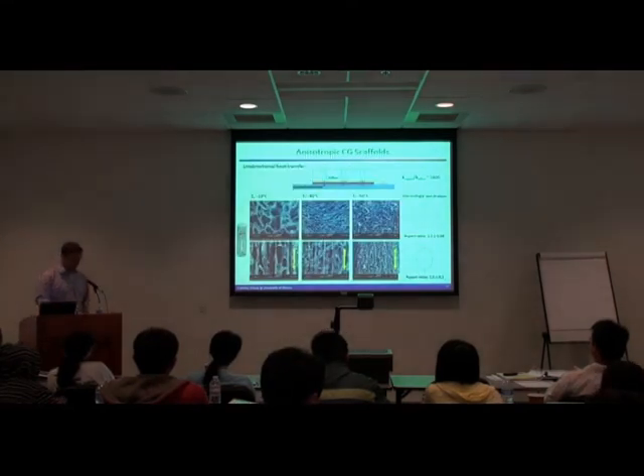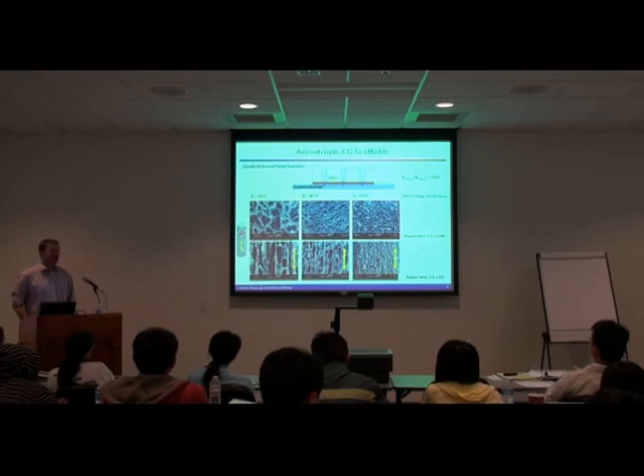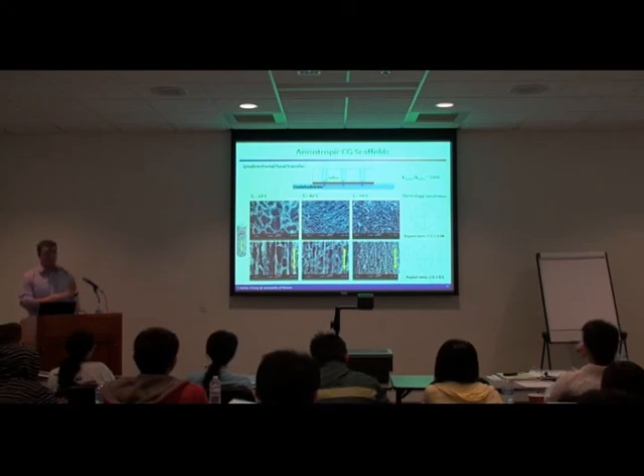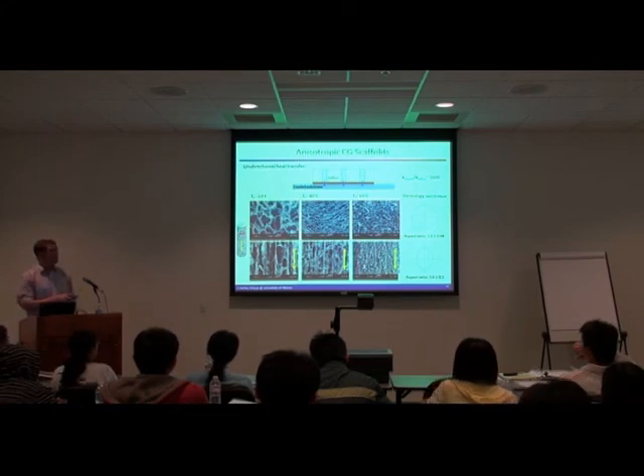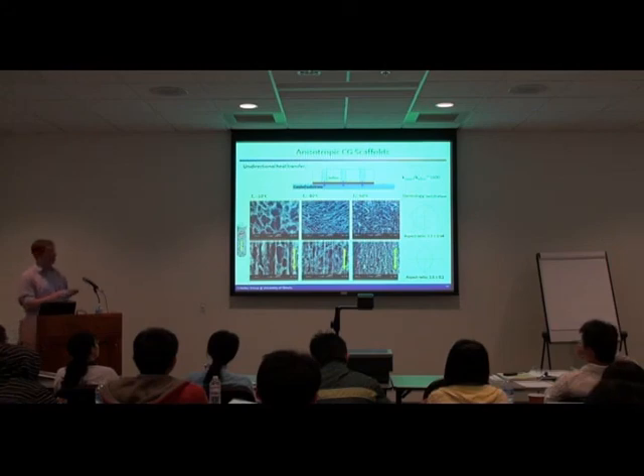So we can start to make highly aligned scaffold structures just by doping the freeze drying process with this idea of directional freeze drying, which is if you take your suspension and put it in a composite mold that has a high degree of thermal mismatch between regions of the mold, like having a copper base on a Teflon mold. The degree of thermal conductivity mismatch is about 1600. So as you start solidifying this, you get really elongated ice crystals forming within it.